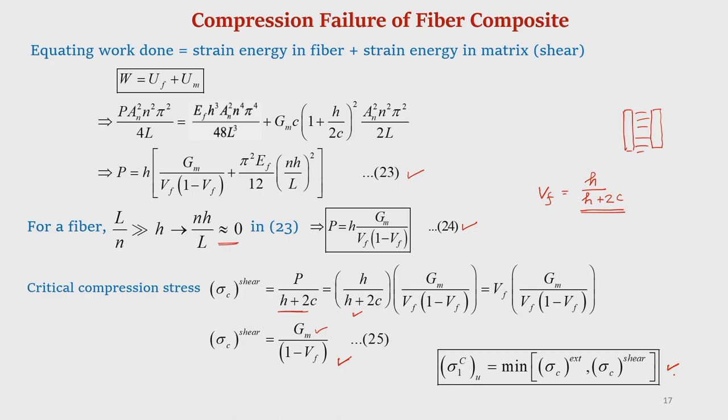Now, having done that, it is observed that whatever we get considering the fiber microbuckling overestimates the longitudinal compression strength. It does not agree well with the experiment. Experimentally, it is observed that the strength we get using this is much higher compared to the experimentally observed strength. Say, for example, in a typical glass epoxy,